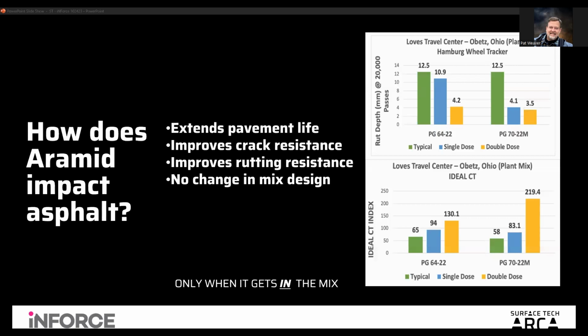The IDEAL-CT, that's one of the crack tests that we have in the U.S. Being 50 states, we have 50 different ideas on how to measure crack resistance. Really not 50, but probably a half dozen. But this just shows graphically, from a control mix, the number of 65 goes up to 94 with a single dose, and a double dose of 130 with one type of binder. And you can see the impact with another type of binder to your right.